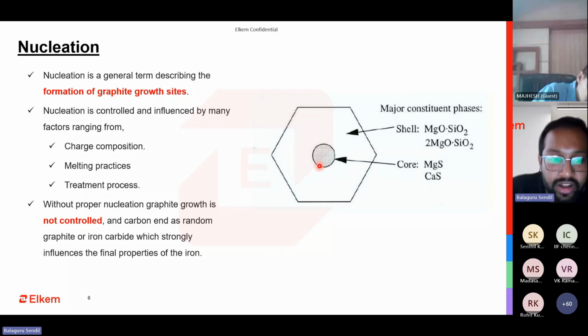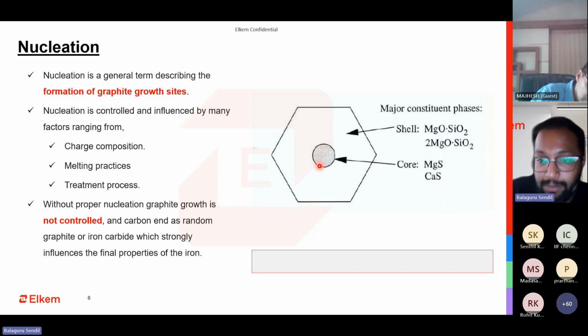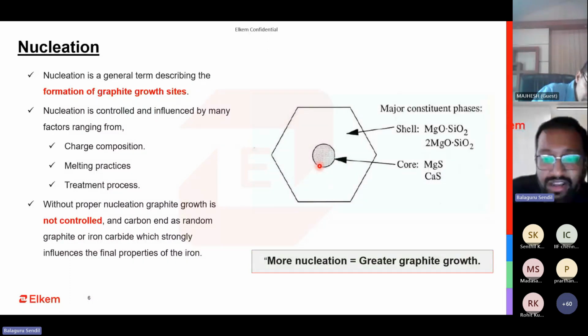What happens is that if you're not able to control the graphite growth sites, and it is growing excessively, then you get a degenerated graphite; you get exploded, chunky graphite, all these issues. But if it is not growing at all, then you can get carbides because there are not enough places for the carbon to come and settle. When this happens, it strongly influences the mechanical properties. When the mechanical properties get changed, the casting will fail or be rejected, or it can have a lot of machinability constraints. So more nucleation is equal to greater graphite growth, but you don't need too much either. Excess nucleation is also a problem.